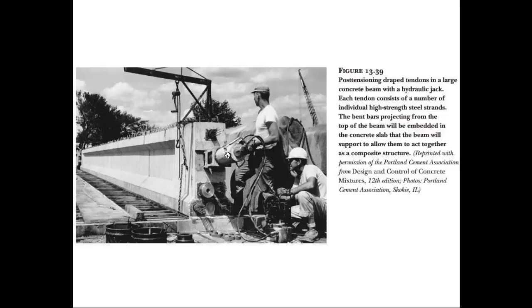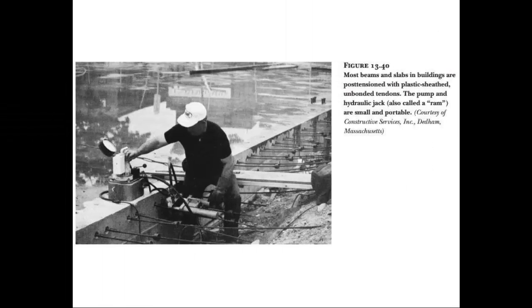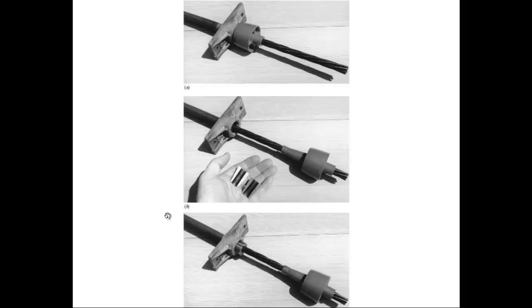Here is a structural post-tensioning beam — a large hydraulic jack is placed on the tendons and brought to a certain pressure, then locked in place for proper strength. For post-tensioning a structural floor, a smaller hydraulic jack pulls on the tendons. Once the right tension is reached, lock bars are slid in and hammered in place. The wedges fit around the pipe and get hammered in, locking that tension on the cable. All of these are tensioned and locked in place, giving the floor its strength and preventing cracking.